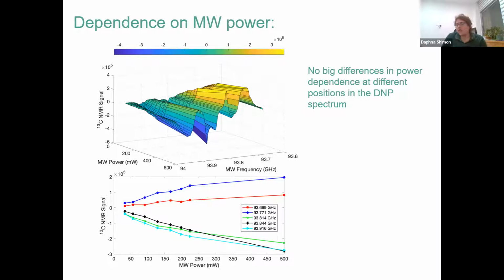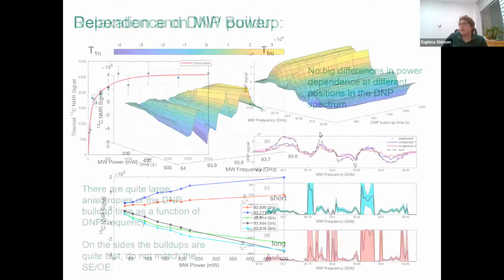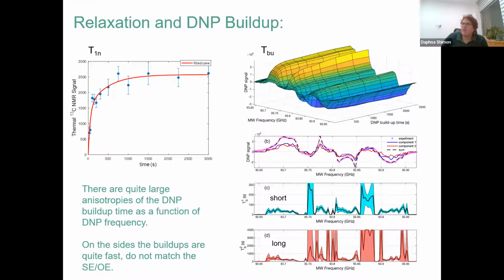The enhancement is expected to go way up if we had more power. And in this range, everything behaves the same, no matter where you look on the DNP spectrum, you're seeing the same type of behavior of the enhancement. So that doesn't help us separate the different mechanisms too much, but the next thing that we did was look at the relaxation times and the DNP buildup time at different frequencies. The T1 of this sample has two exponents, a short time scale and a long time scale. And when we look at the DNP buildup time as a function of the microwave frequency,